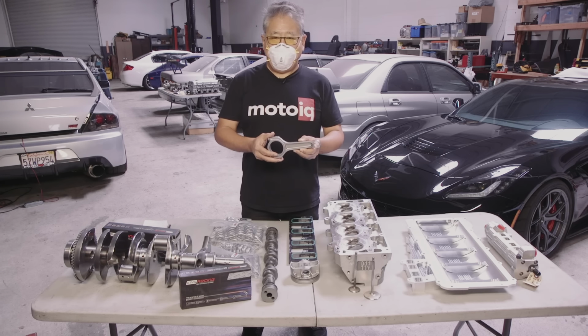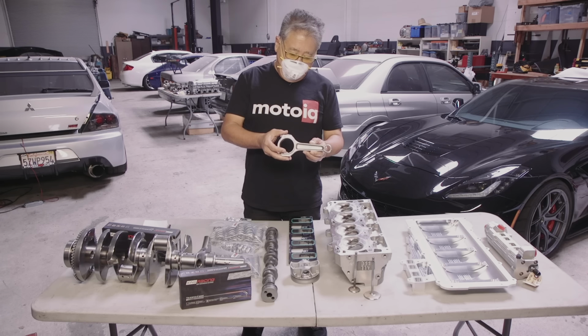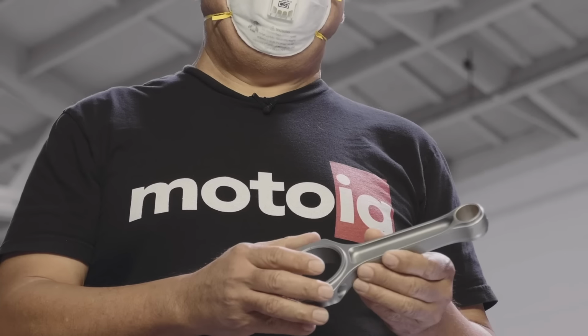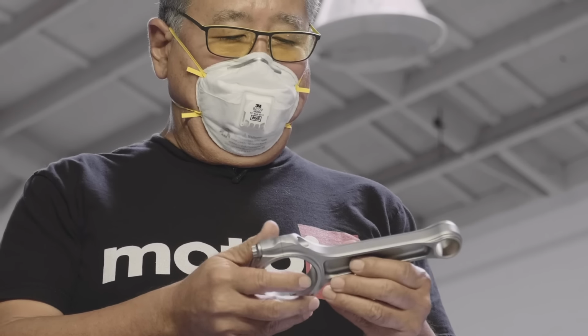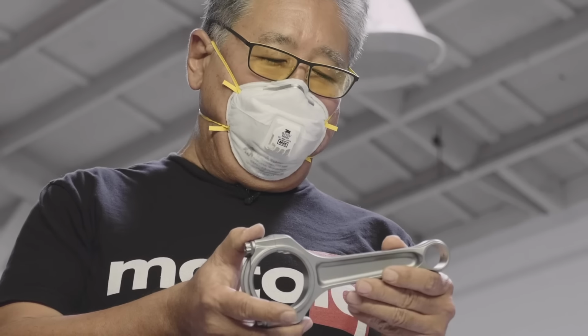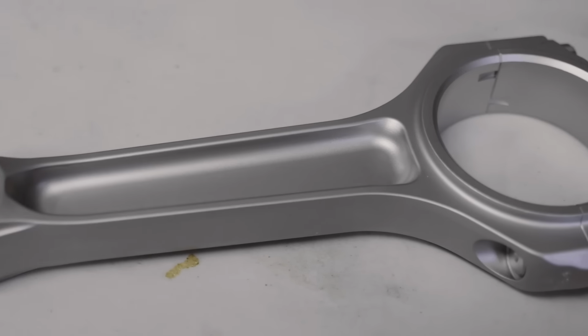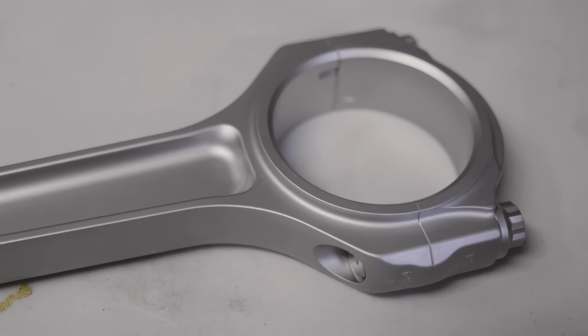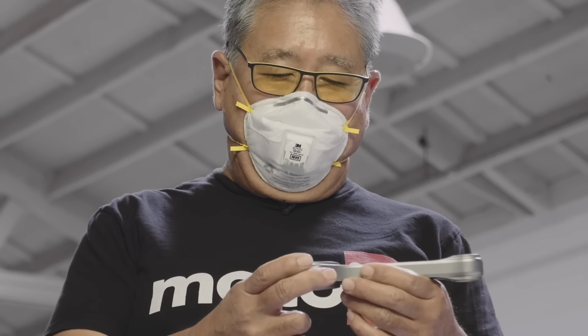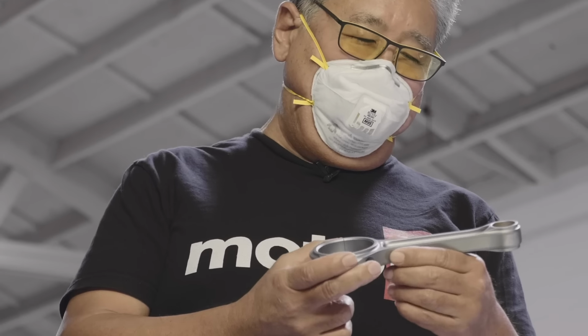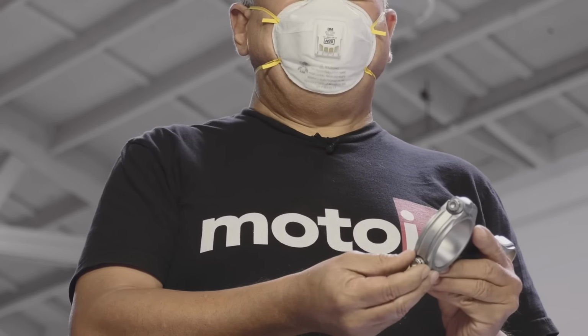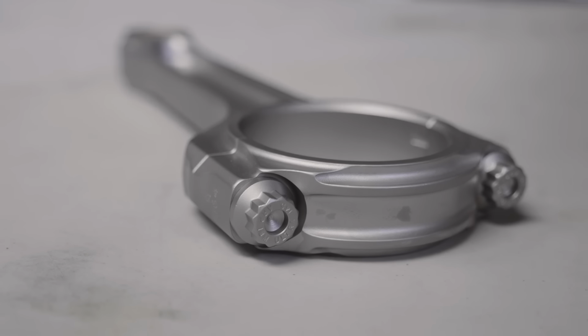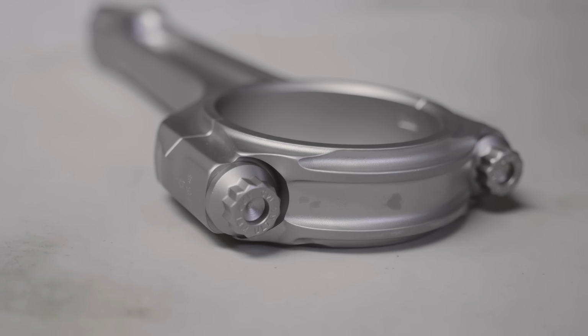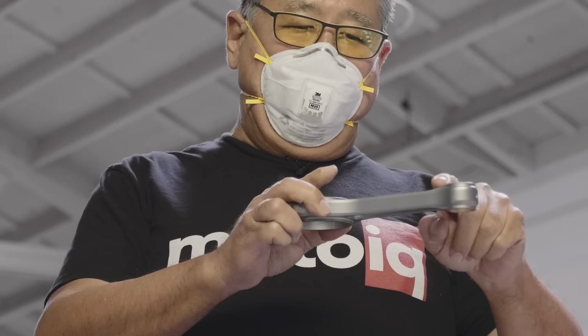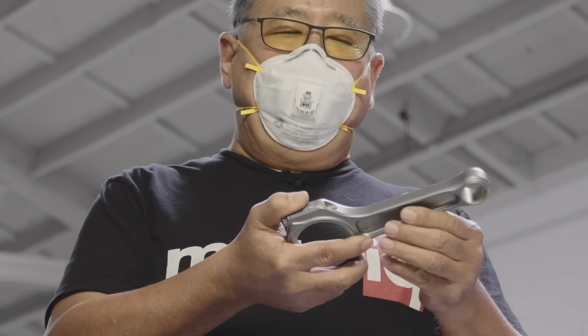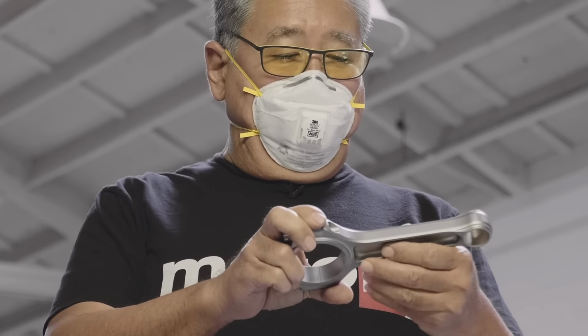Now we use a Callies Ultra I-beam rod, which is their top-of-the-line, strongest rod. Like the crank, the rod is made out of Timken 4330 vacuum degassed, high nickel, high chromium alloy. Super tough, proprietary alloy, vacuum degassed to eliminate internal voids and things that can cause fatigue crack starting sites. It has ARP custom-made 625 bolts, which are a step up from the typical ARP 2000. Really good bolts. The whole rod, every corner and every radius, is rounded, so you don't have any place where a stress riser could start. This is a really nice rod.